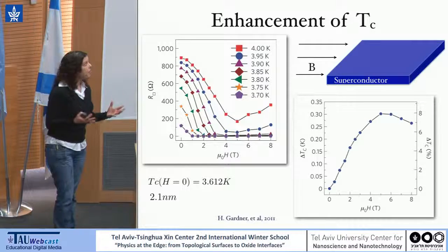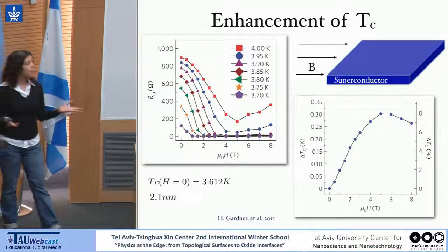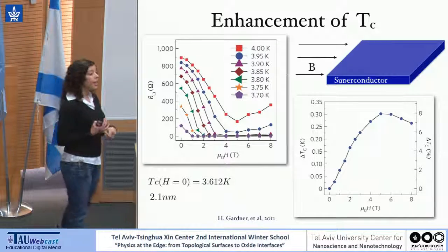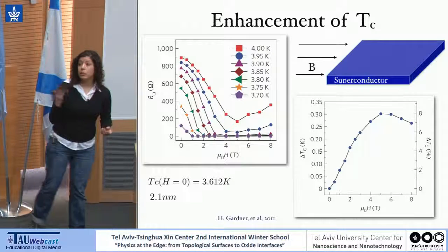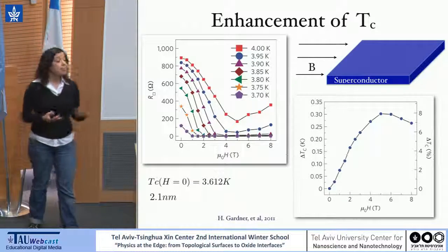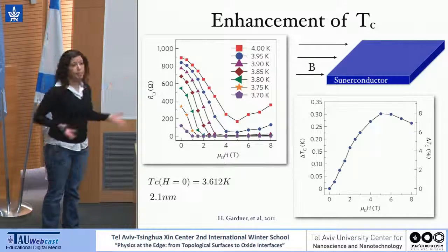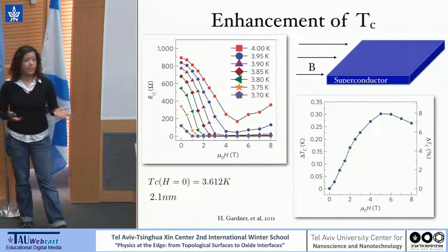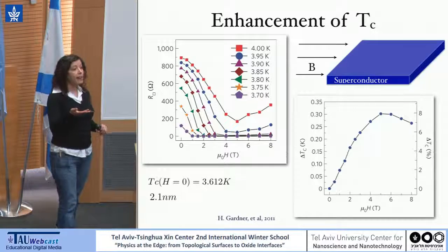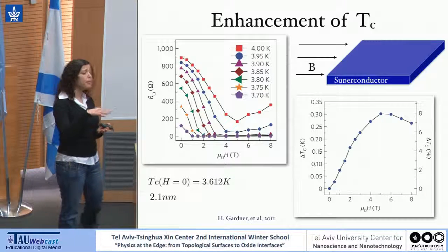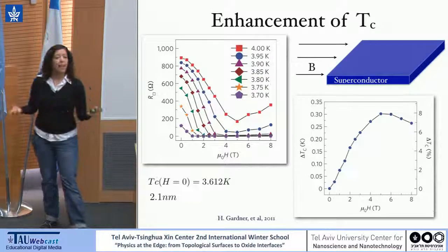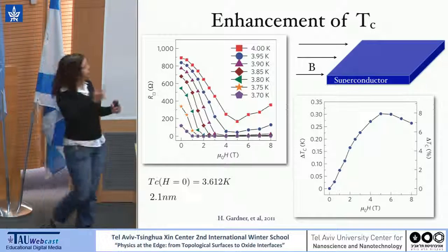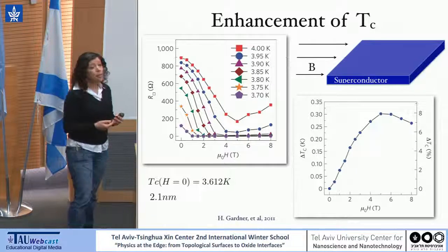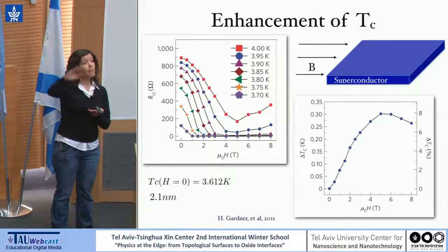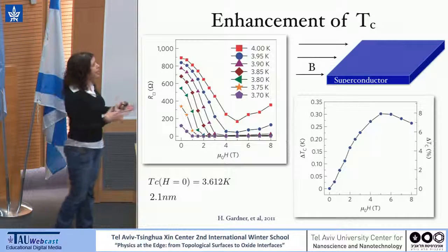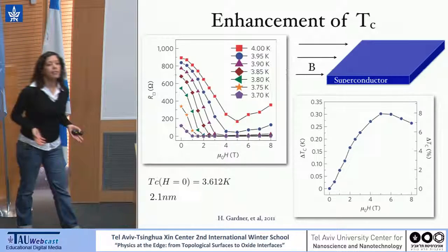Now, one can imagine that in both these kind of systems, so we said it's LAO-STO and lead, we have strong spin-orbit coupling. So one can imagine maybe there are magnetic impurities in such system, and what the magnetic field does is basically to align the magnetic impurities and turn them into regular impurities. And since from the previous measurement we know that the system can survive up to very high magnetic fields, basically the entire effect is just to eliminate the magnetic impurities.